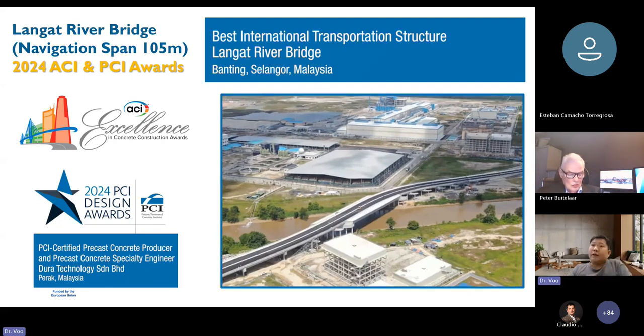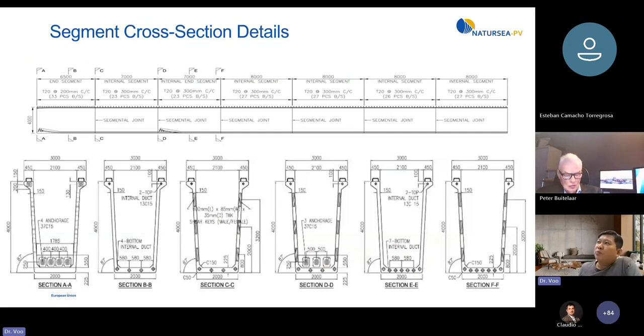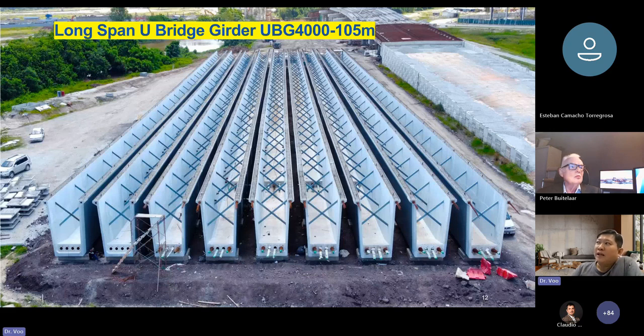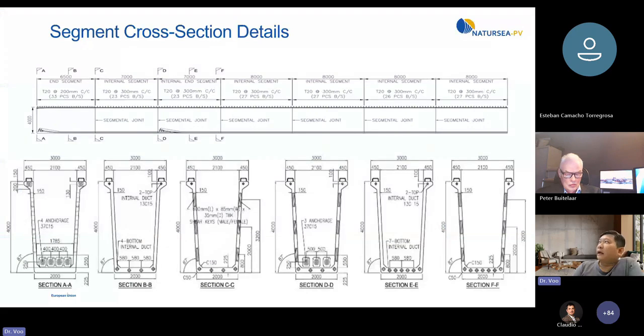So the UHPC we use for this project is basically to cast a precast U beam, which are assembled at the site using a post-tension method. One U beam is around 105 meters long and weighs around 400 tons. Okay, and one full beam has about 14 segments. Each segment is around 6.5 to 8 meters in length.